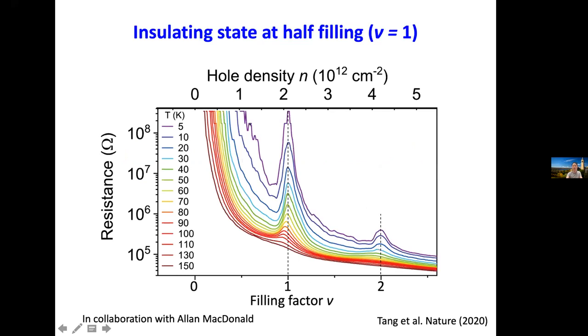Let's first ignore this very low filling part when the contact resistance goes up like crazy. So when you increase temperature, those peaks sort of gradually disappear.